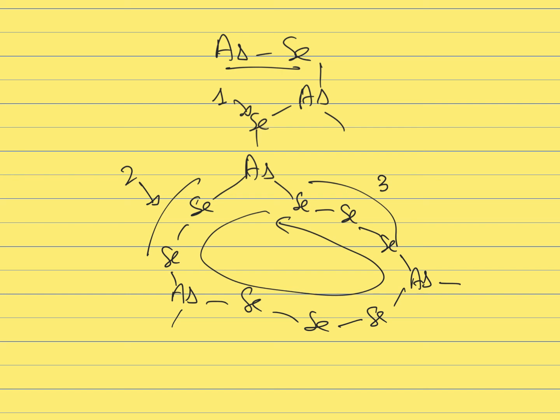In the same way as for germanium selenium, typically in arsenic selenium you rarely have arsenic homopolar bonds. They are possible, but they are not very common, especially when you have a low fraction of arsenic in the glass. On the other hand, you will very commonly have some selenium homopolar bonds. And of course, you will find some arsenic selenium bonds. So in chalcogenide glasses, you can have any combination of those elements.